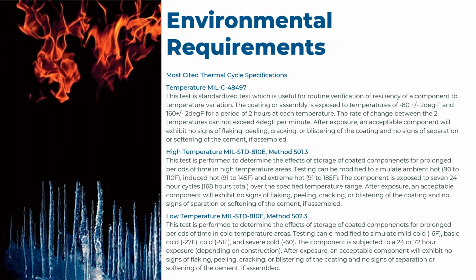Super high temperature tests for optics that are going to be used in the desert, in assault vehicles, gun mounts, that sort of thing, would probably fall more into the MIL-STD-810E, and you can read that specification there. Obviously, 7 24-hour heat cycles, 168-hour test overall. That is an extremely aggressive test, but if your optic is going to be used in an aggressive environment, you probably want to consider using that.